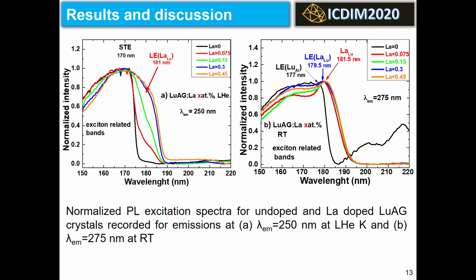The same trend is observed in the excitation spectra recorded at room temperature and at 275 nanometers, where the bands in the excitation spectra, both recorded at liquid helium and room temperature, are located on the boundary of the fundamental absorption edge.